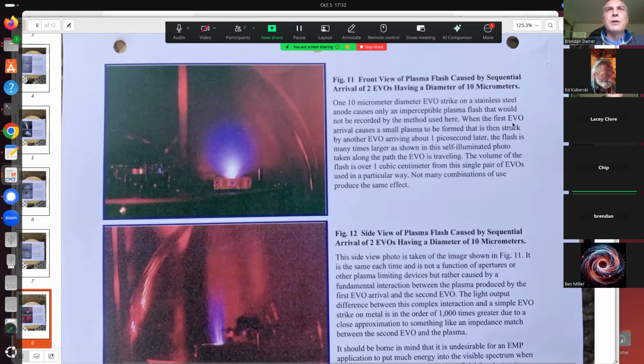When the first EVO arrival causes a small plasma to be formed, that is then struck by another EVO arriving about 1 picosecond later. The flash is many times larger, as shown in this self-illuminated photo, taken along the path the EVO is traveling. The volume of the flash is over 1 cubic centimeter from the single pair of EVOs used in a particular way. Not many combinations of use produce the same effect.